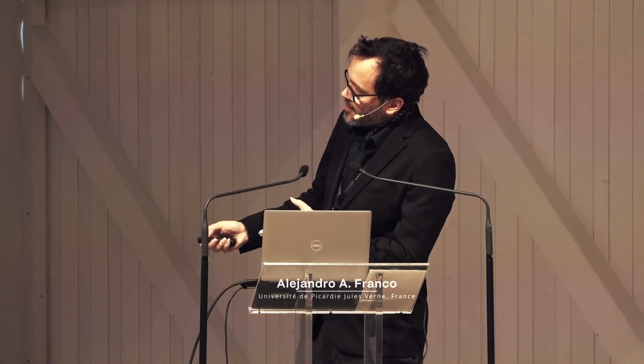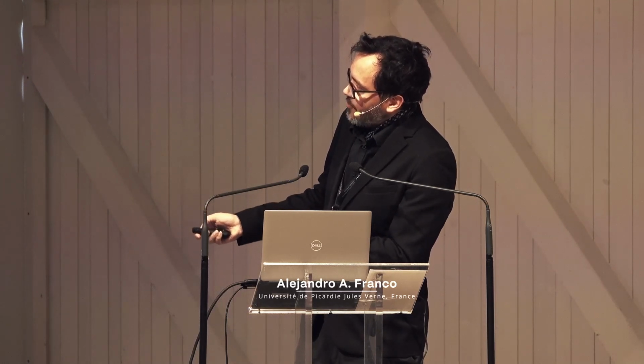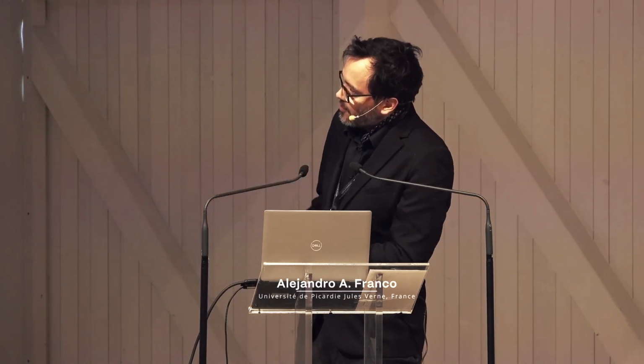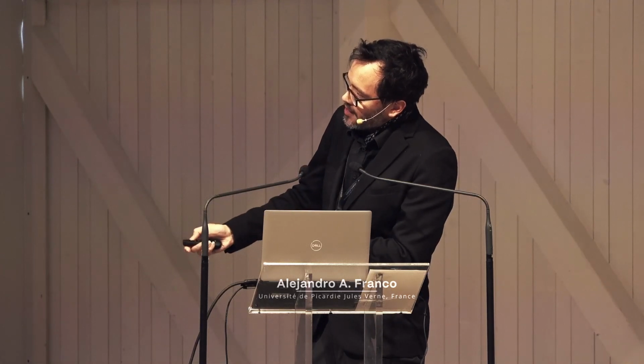And now I'm going to speak at the end about this optimization, which closes the loop. Here we use in particular Bayesian optimization. We use this complex manufacturing simulator to produce a lot of electrode microstructures that we have characterized in terms of properties, once again porosity, thickness, composite conductivity, and so on. We have derived then a machine learning model able to correlate the manufacturing parameter values that you want to apply and the properties that arise from these manufacturing parameter values. Here we explore 3 dimensions in this problem: the formulation of the slurry, the solid content of the slurry, and the compression degree in the calendering step.